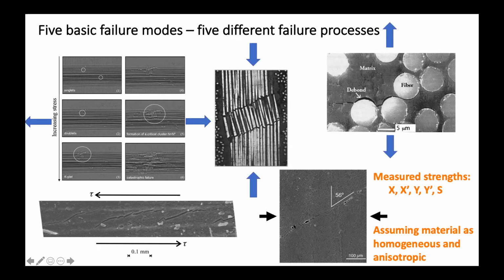If you apply compression, the failure occurs on an inclined plane, which is not at 45 degrees. Then if you do in-plane shear, axial shear, the failure is actually nothing to do with any of the other failure modes.